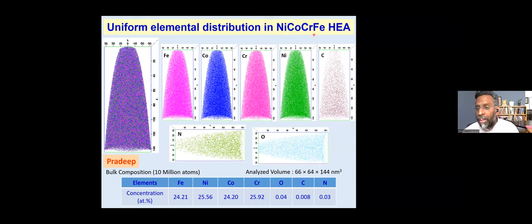You can also see where is carbon, where is oxygen, where is nitrogen. You can actually see very small atomic number elements also inside. In most of the other spectroscopy techniques, it is very difficult to see atoms which are of a smaller atomic number. Here you can actually see. And you can measure the composition by picking up a small region and doing a quantitative analysis. And you can see here, the composition can be clearly seen.